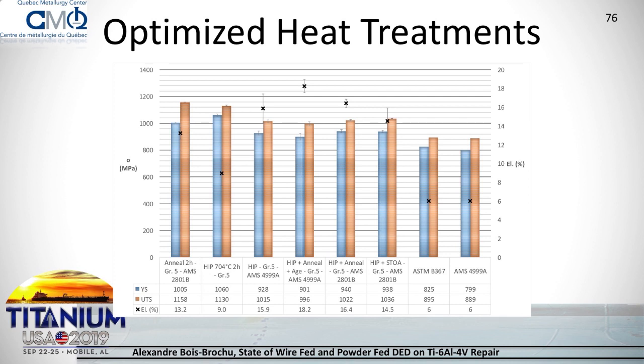Meanwhile, for those requirements, in a lot of applications it will still be required to do some hipping for various concerns. So if you need to do hipping, hipping only can produce quite high mechanical properties. And then again, for various requirements, a lot of people do hipping and then another heat treatment afterward. Then it should be an annealing at a relatively low temperature, so the 704, in which you'll have quite high mechanical properties over here.